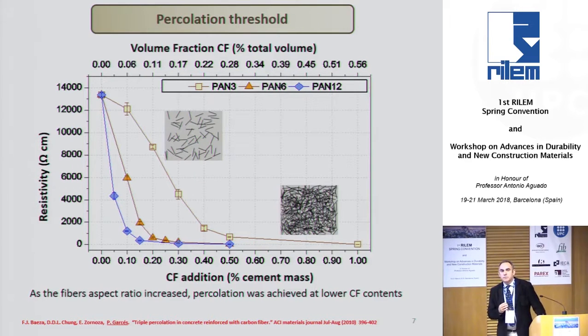Let me introduce two concepts related with my talk. The first one is percolation threshold. In order to limit the carbon additions, it is important to know the value of the property called percolation threshold. Percolation threshold comes when there is enough density of carbon fibers to establish a continuous path for electricity. Once the percolation threshold is reached, it is not necessary to add any more carbon fibers; it makes no sense because resistivity doesn't change significantly.